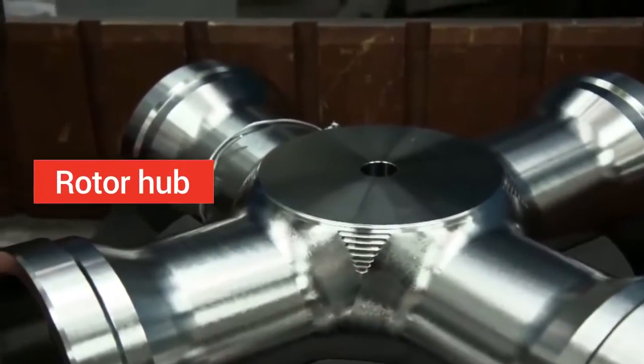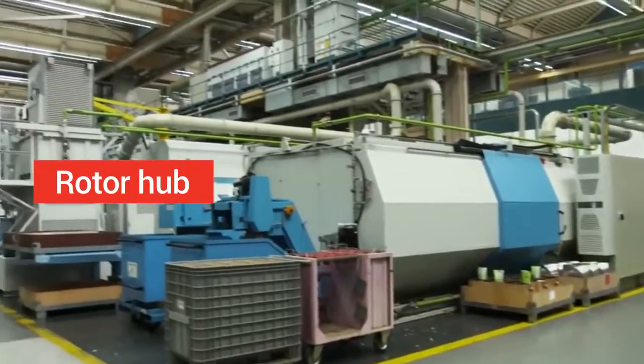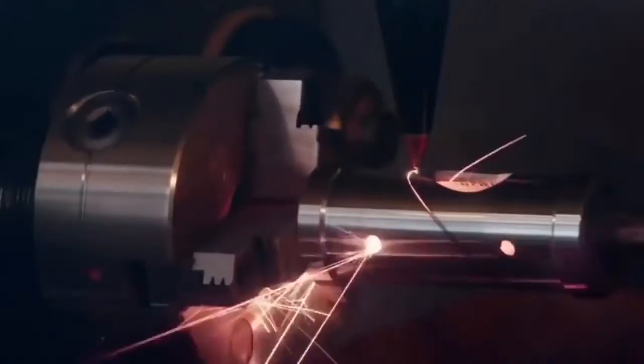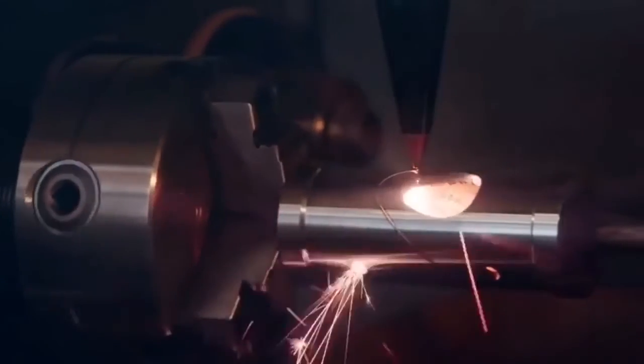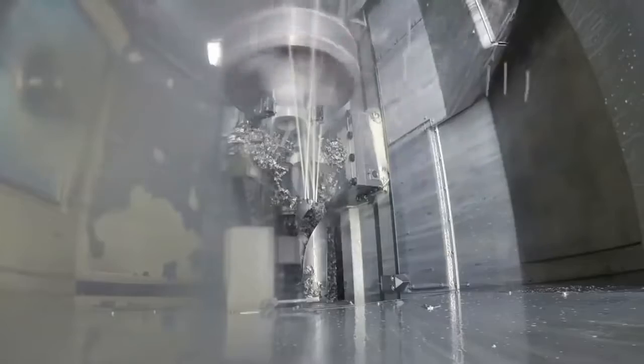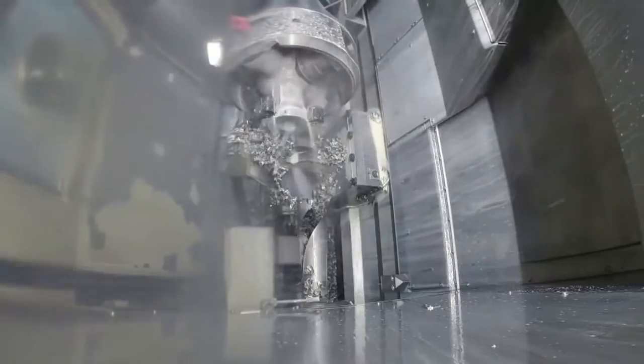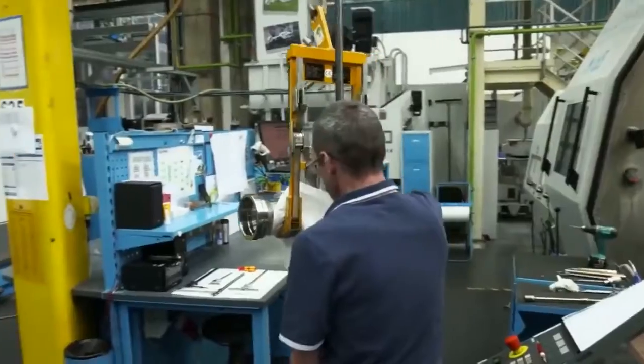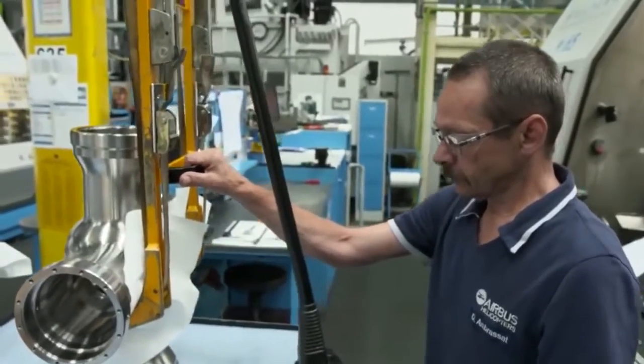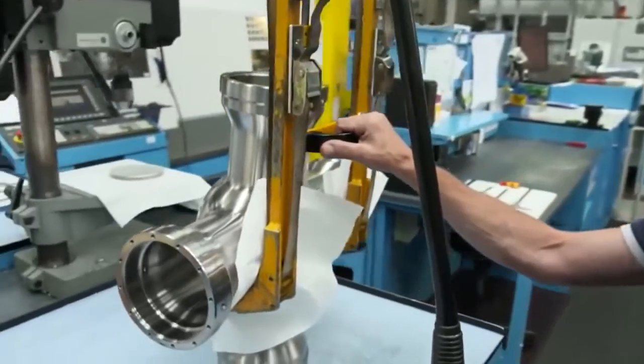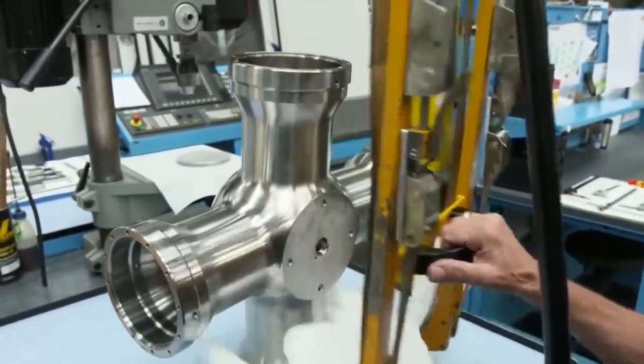The rotor hubs. The rotor hubs are created in the metal cutting departments with high-tech milling machines, shaped from forged titanium blanks with an accuracy of 1,000th of a millimeter. The hub has to be absolutely round, that's why it is given up to 10 days of rest in order to recover from the high tensile forces. The hub can weigh 150 kg or more. When finished, it's worth 25,000 euros.